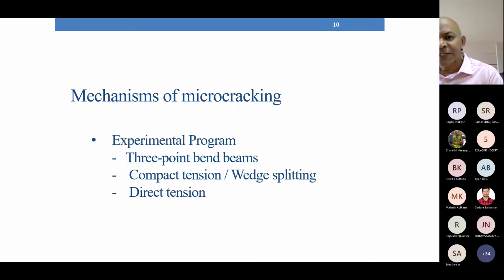Firstly, I will present some of the results of the experimental work which we have carried out. We have used 3-point bend beams under flexure. We have used compact tension and wedge splitting specimens, and we have also performed tests under direct tension. Here I would like to acknowledge the huge grant of almost 3.5 crores given by IISc to procure a biaxial fatigue testing machine. I also acknowledge the contributions made by Dr. Sundar in designing this machine for our requirement. I will be showing some of the results of the direct tension in the next slides.